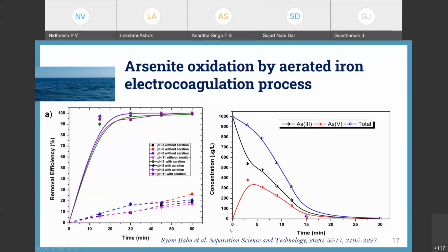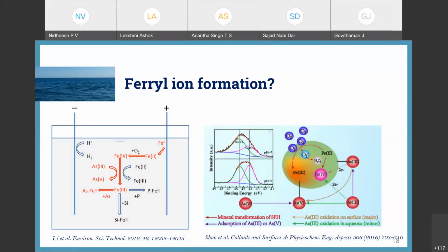Then these results are already published in Separation Science and Technology. It's available online. Then we checked what are the possibilities. Yeah, then in 2012, a similar work from the University of Berkeley group, that means the Gadgil group, they already published one paper. They mentioned that if you are aerating, the Fe0 will come as Fe2+, and the oxygen will convert Fe2+ to Fe4+. They proposed a mechanism stating that this oxygen will convert to hydrogen peroxide, H2O2, and this hydrogen peroxide is an oxidant, so that will convert Fe2+ to Fe4+. But this reaction will not take place in the water, because hydrogen peroxide will not be generated in any electrolytic system by only oxygen addition to an Fe system. But they also mentioned the ferryl ion formation. That's why this oxidation takes place.